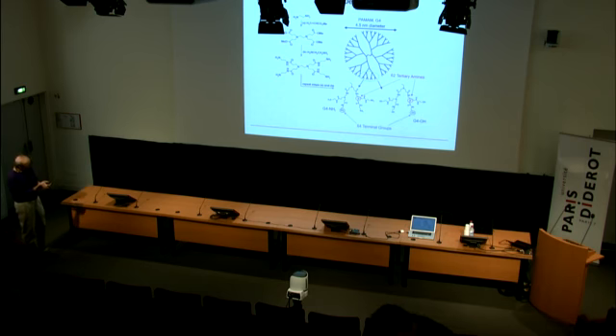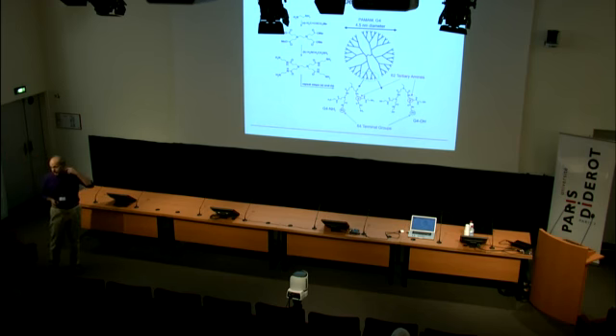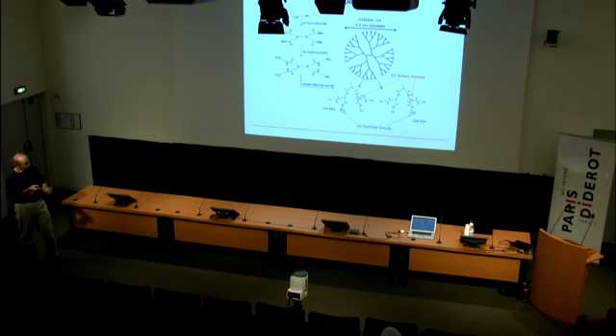And now you can go through this cycle again, and in the next iteration of 2 reactions, you go from 4 to 8 amines, and you can keep doing this up to about 10 cycles. And then finally, there's so much steric crowding on the periphery of the dendrimer that you can't keep doubling the number of terminal groups on the dendrimer. Now, by the time you've done these reactions about 4 times, there's enough steric crowding that the polymer no longer is planar, but it starts to adopt a globular shape as these end groups here try to get out of each other's way. And so this is a planar projection of what's really a 3-dimensional object.